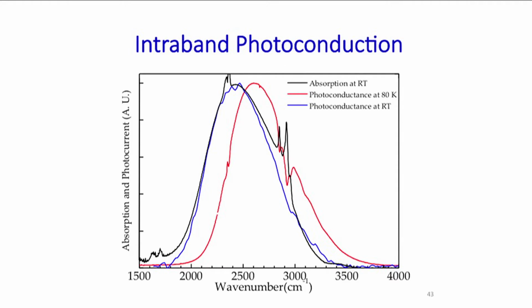And the systems can then be used to detect infrared radiation. So this is a film of those particles, dried now inside a cryostat. We measure the absorption of the film. This is the black line, contains some CH contamination. We measure the photo response of that film. It's not very good, it's noisy, but it's exactly at the same position.